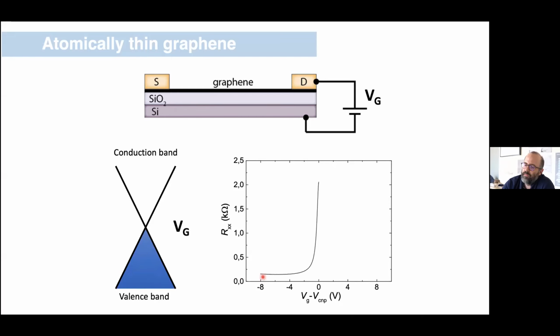And what you see is that the resistance is very low. That's because graphene is an excellent conductor. But the resistance grows to some large value at zero bias. And that happens not because I'm necessarily introducing any disorder or anything like that. It's just that I'm squeezing it down to becoming nearly a semiconductor or nearly an insulator. There's very few density of states available at this crossing point here. And because of that low density of states, in a sense, resistance goes up. But I can continue to gate this, and what happens is now I recover a low resistance state, et cetera.